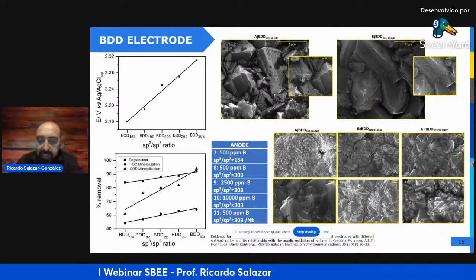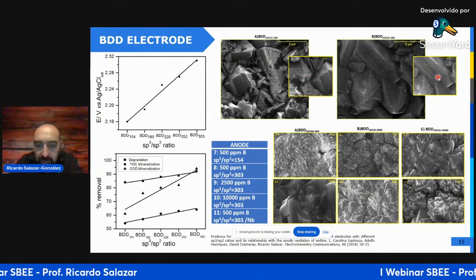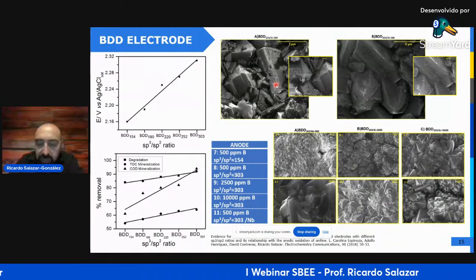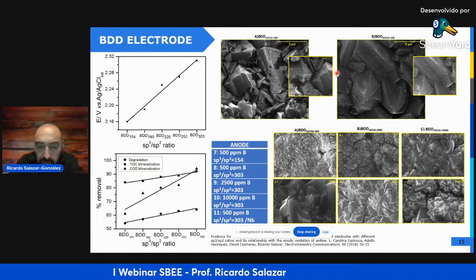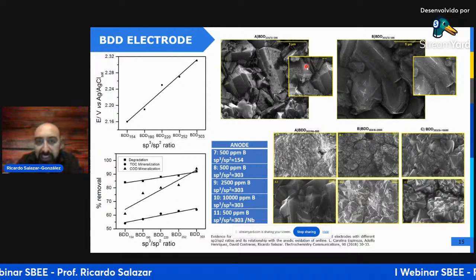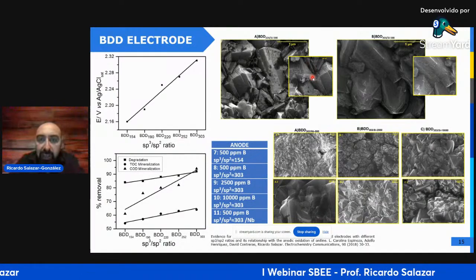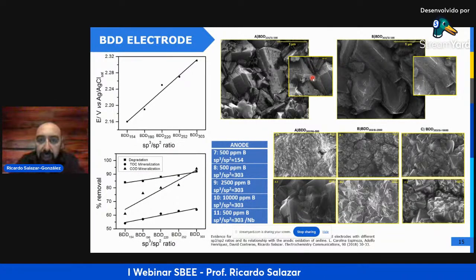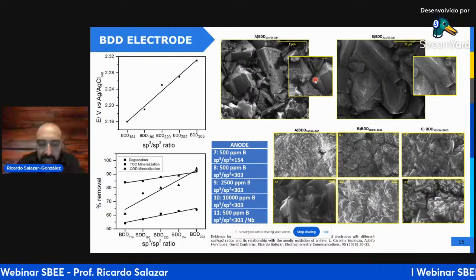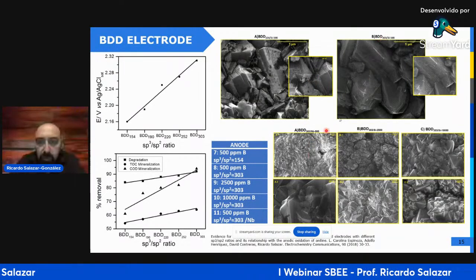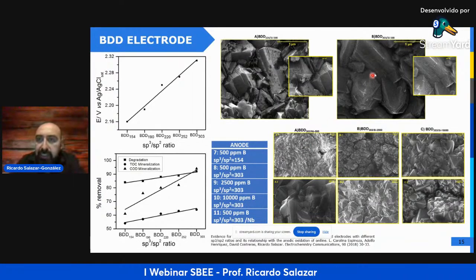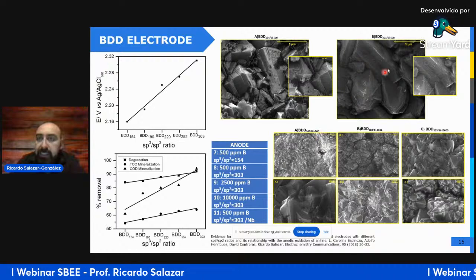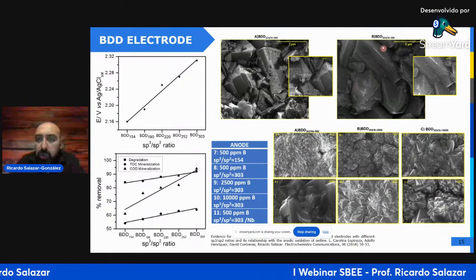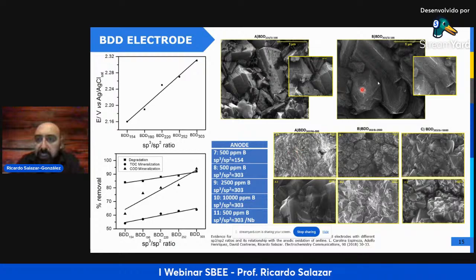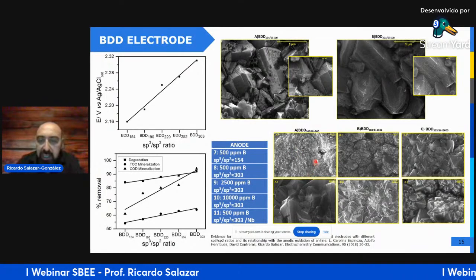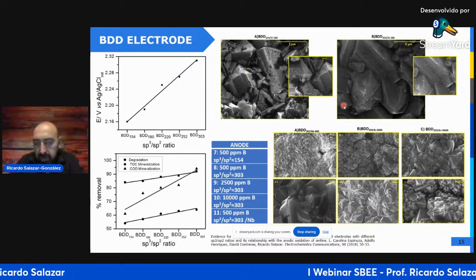If we increase the magnification here, you can see it is possible to observe a great number of defects on the surface, and these defects are higher when we have more concentration of graphite on the surface. When we change the support, for example, this is the same ratio of graphite and diamond, with the same concentration of boron, but with a different support. This is silicon and this is niobium. The surface and the morphology are not affected by the support.